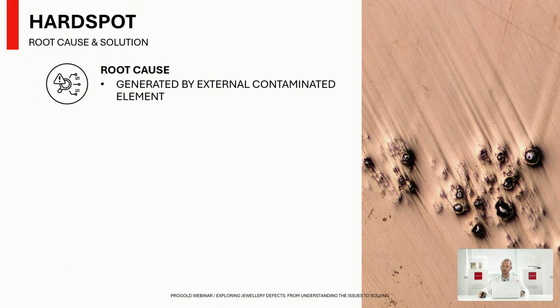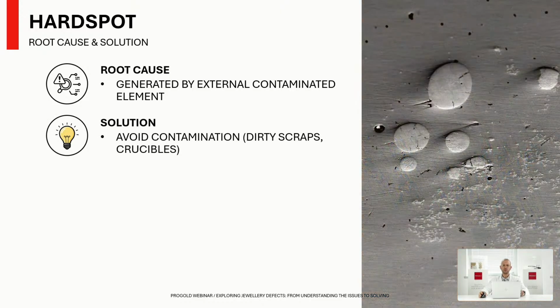Which is the cause of this defect? Mainly, this defect could be generated by an external contamination, generated by the contact of the alloy with other kinds of elements that are present during the production process. The solution will be to avoid the contamination by not using dirty scraps that come from different production processes, or using the same crucible for different kinds of alloy.